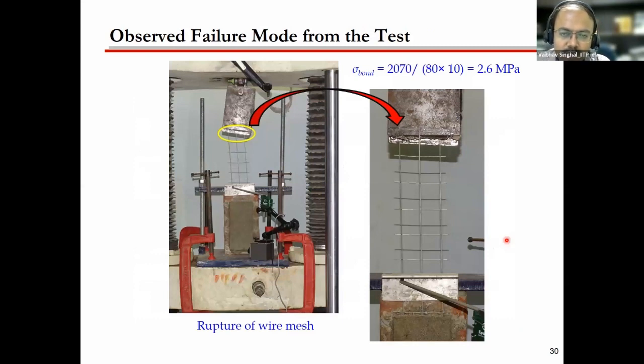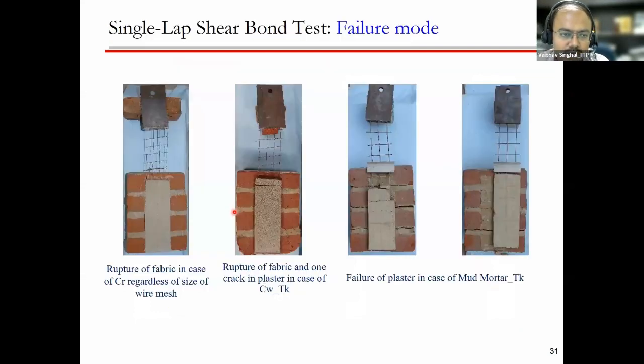Now here we have done the test with the steel wire mesh. And the failure which we have seen is the tensile rupture of the wire mesh before the debonding failure. So these are some more failure modes. As you can see, in the first case, we found the rupture of the fabric or rupture of the wire mesh. And in some cases, we found the failure in the cementitious matrix also. Now you can see here, there is a lot of failure in the cementitious matrix. And in this case, you can see a complete debonding.